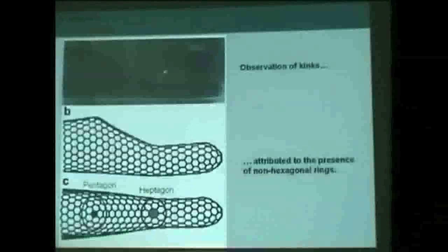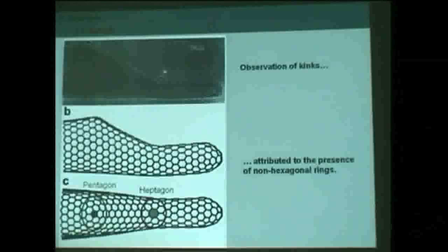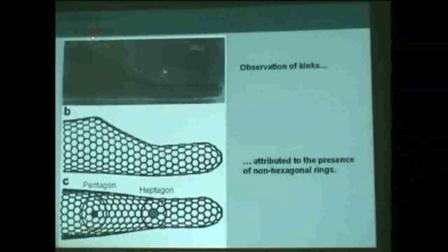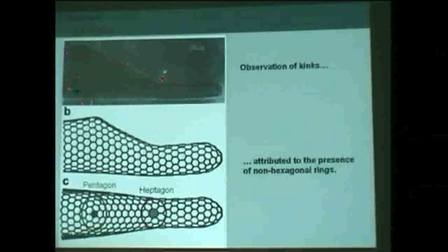Alright, defects. I'll go a bit fast on defects. So those materials, as any materials, are not perfect. It can be observed, for instance, in this TEM image, that in this multi-wall nanotube there are some kinks, kinks going upward or downward. How do we explain those kinks? Like an elbow, these kinks are very localized. It's not a smooth change of curvature - it's a very localized change of curvature. What happened there?